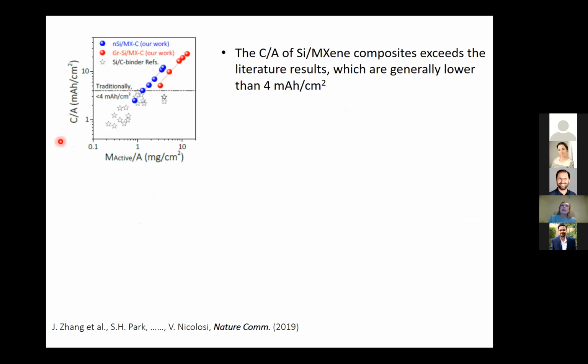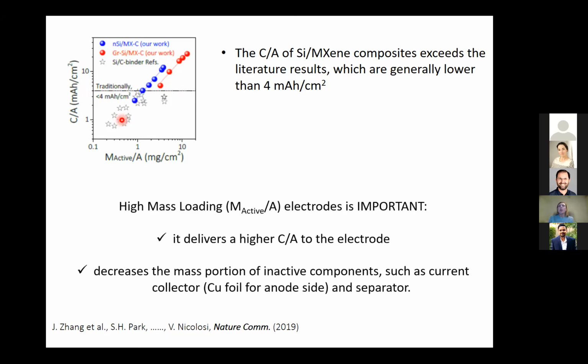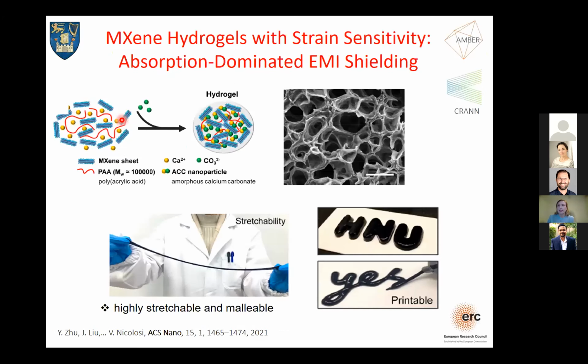But this is a very nice graph where I show the areal capacity as a function of the active material. And here you see the performance of our electrodes based on MXenes and silicon versus the traditional battery that you find on the market, which can achieve traditionally about 4 milliamps hour per centimeter square. So we could achieve high mass loading and deliver very high areal capacity.